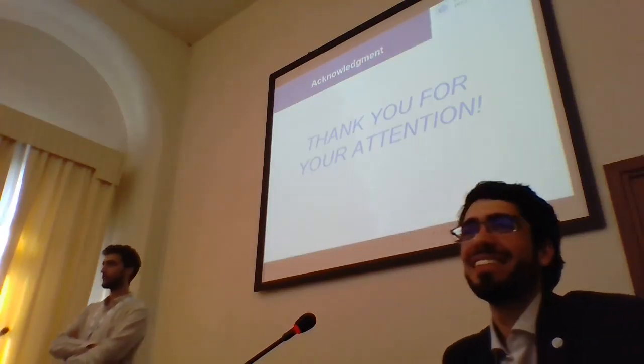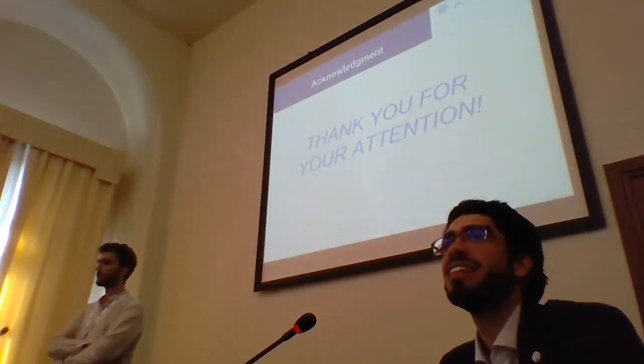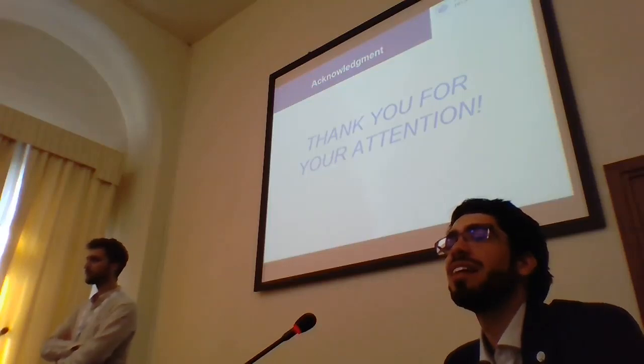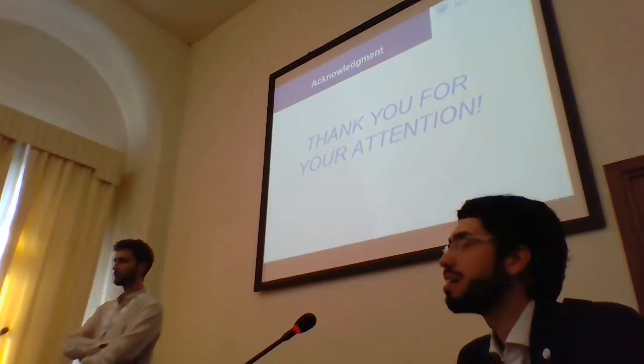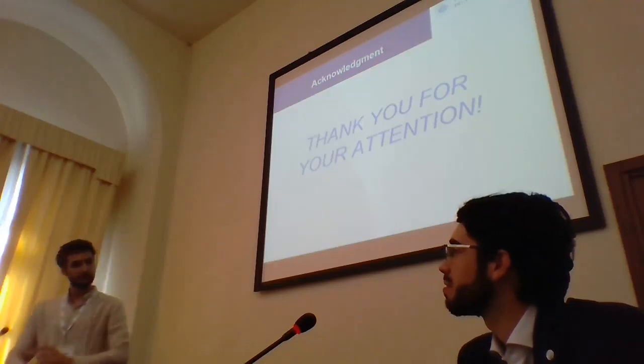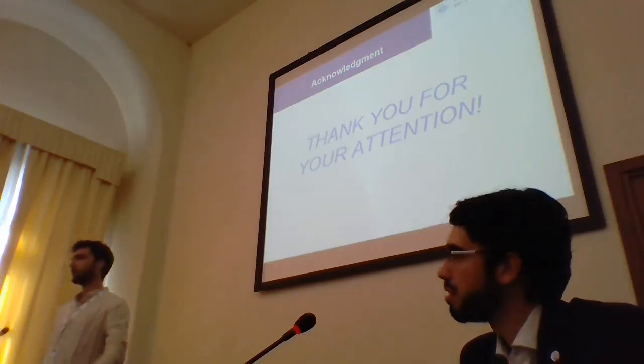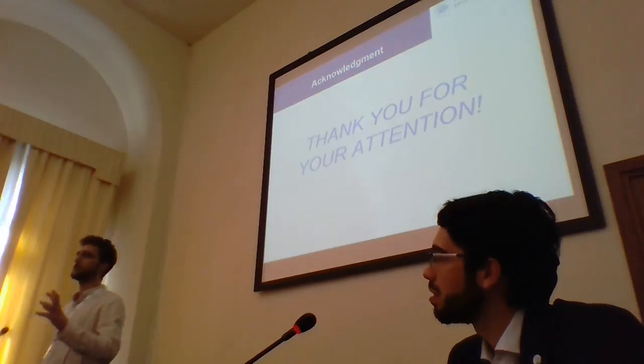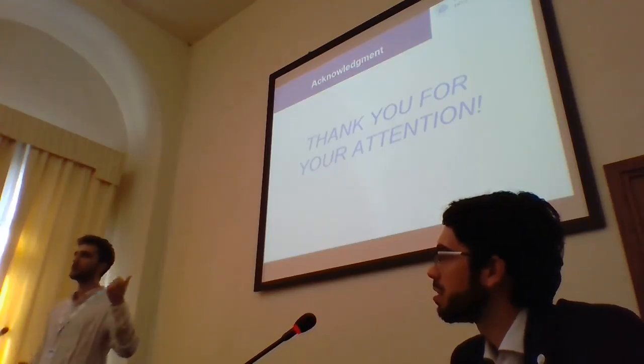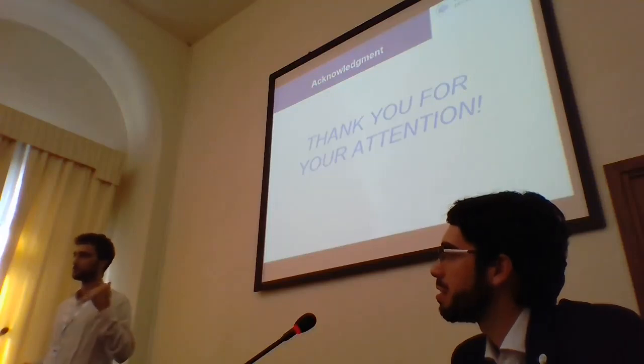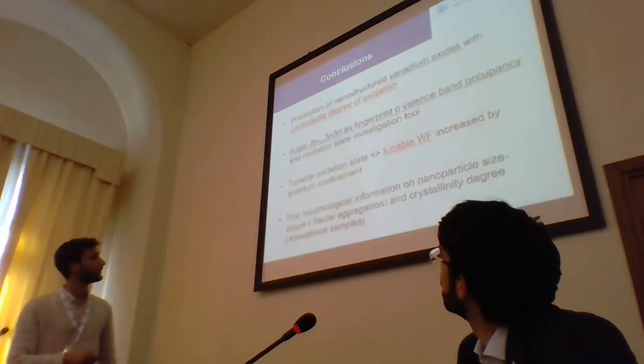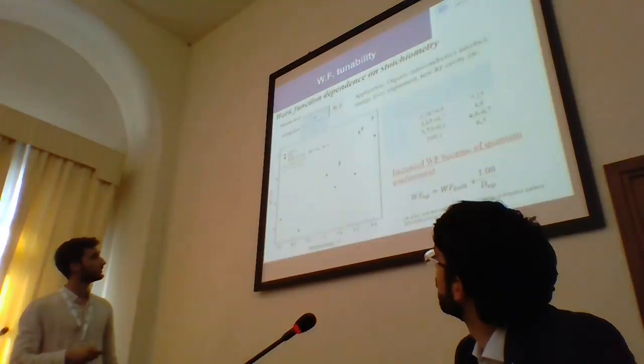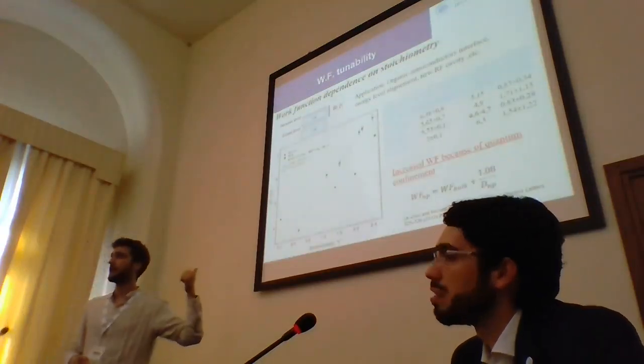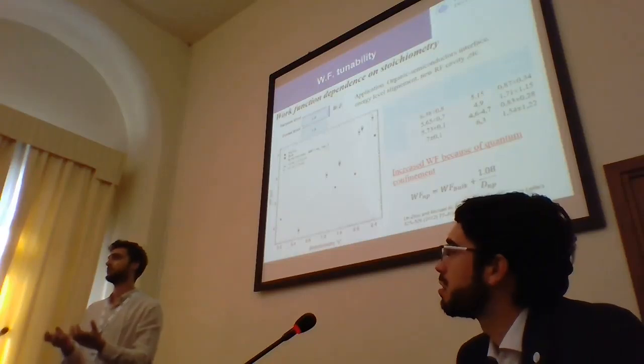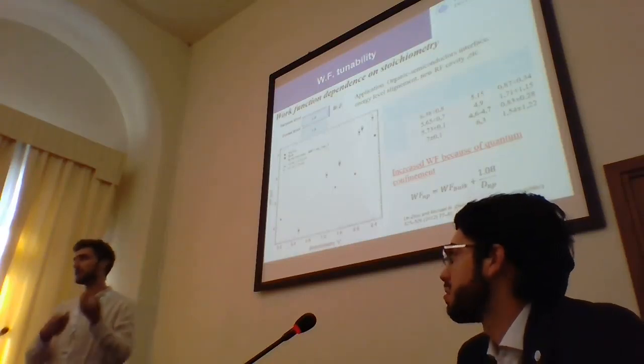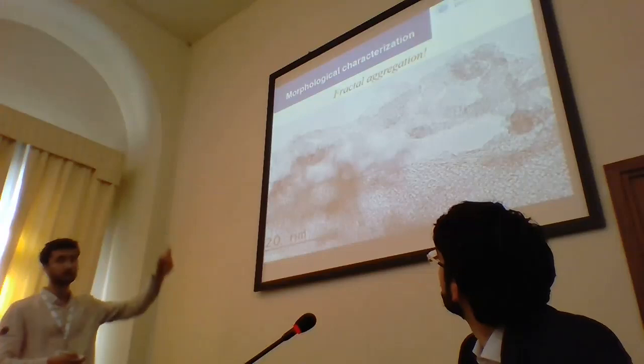Hello, you mentioned the fractal aggregation. Do we know the dimensions of the aggregation, is it between 2 and 3 or between 1 and 2? It's actually between 2 and 3. When I said between 1 and 2, it was an extrapolation from the equation of the work function I showed you before in this slide. But this equation relies on the approximation that the nanoparticles are perfect spheres, which is not the case, of course, since they are this ugly stuff.